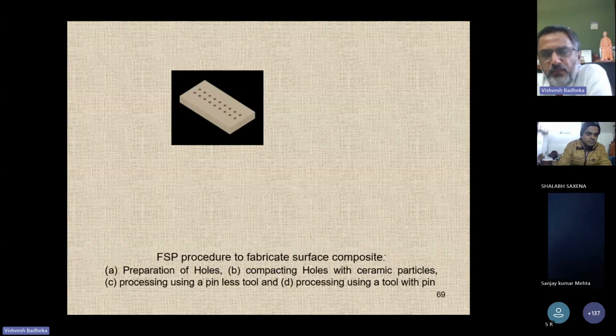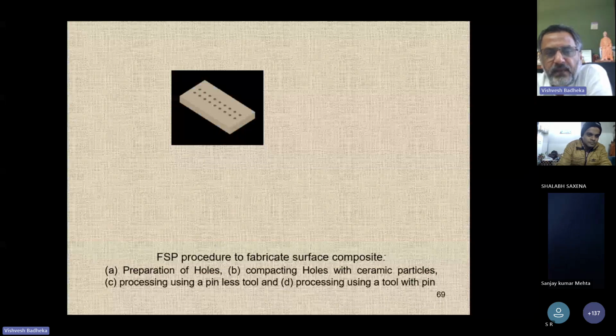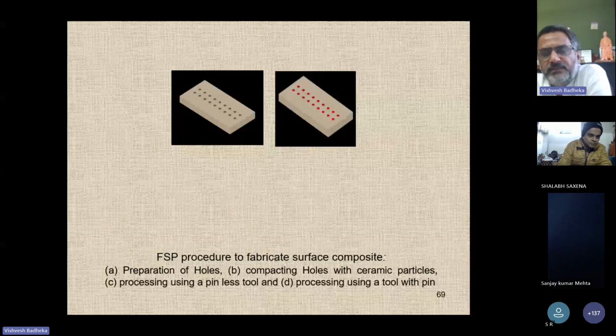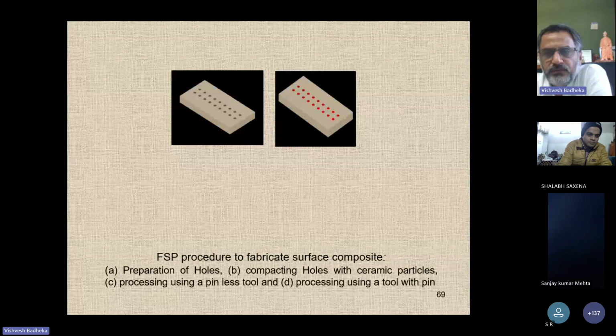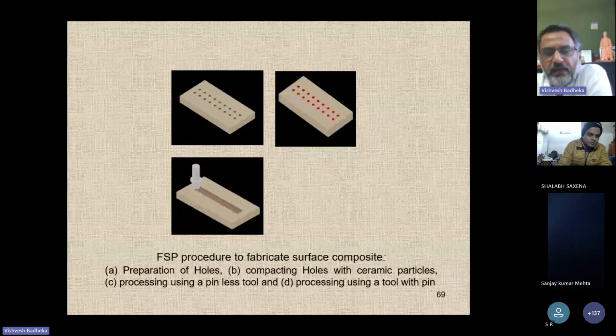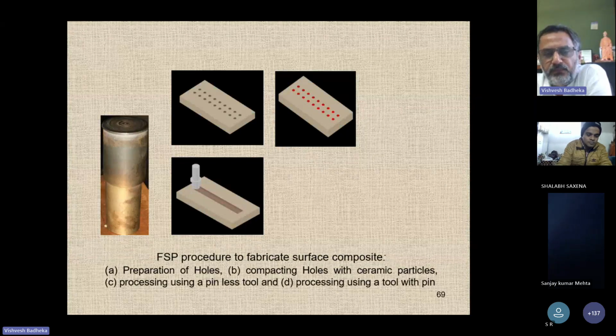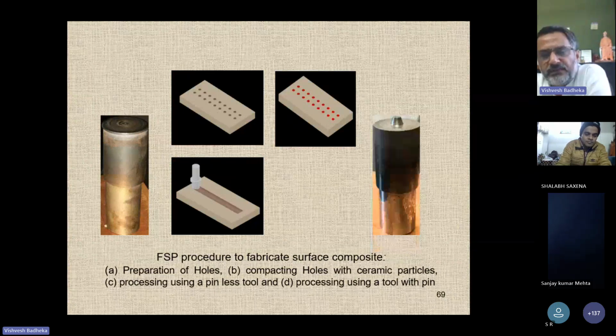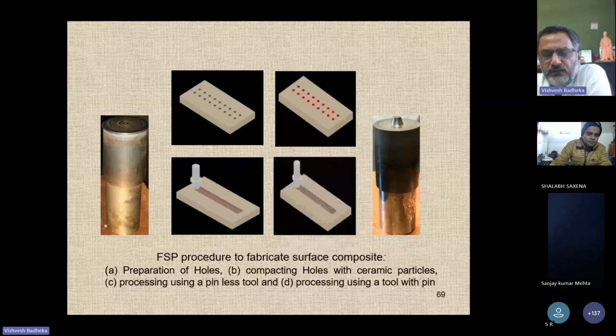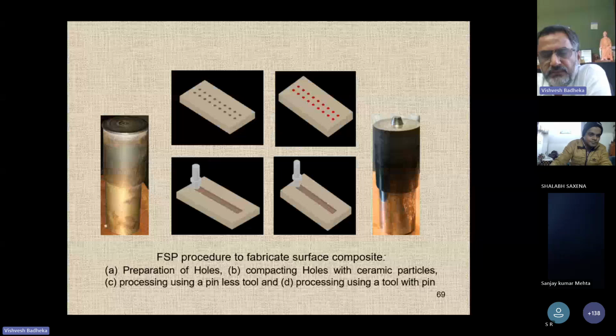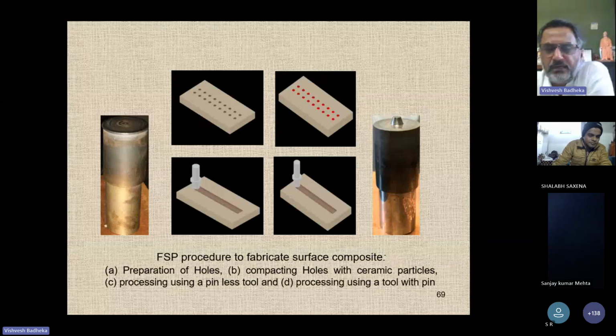So you take a plate, an aluminum plate for example, and create blind holes, and these blind holes are filled with the reinforcement. Then you close these blind holes with the help of a tool, which is a capping tool. You don't have a pin here, right? Then after capping, the same area is processed again with a tool which has a pin. This is called the stirring tool, or stirring pass.